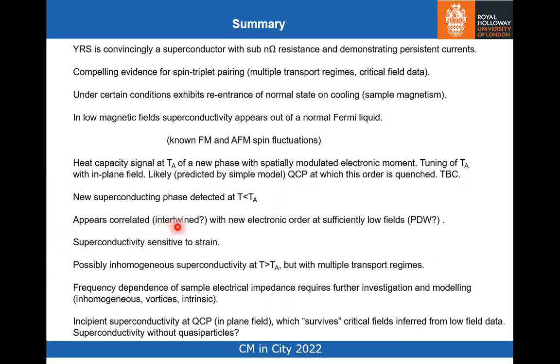It appears to be correlated and maybe even intertwined with this new electronic order that appears at TA in low fields, a candidate for a pair density wave. The fact is that the superconductivity is very sensitive to strain. So we're worrying about inhomogeneous superconductivity at temperatures greater than TA within these multiple transport regimes. The frequency dependence of the sample electrical impedance needs further investigation, because that will help us model these various candidates for the origins of the sample inductance, to do with inhomogeneous effects or vortices or some intrinsic behavior.